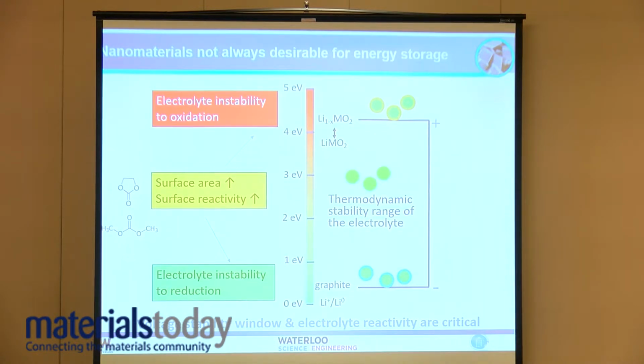One sort of stabilizes these systems somewhat by kinetics. So the higher the surface area, the more the surface reactivity. And therefore, nanomaterials themselves are often actually a detriment for energy storage. But it depends on what the voltage window is. So if you can make your cell work within these narrow limits, then nanomaterials are much more favorable.